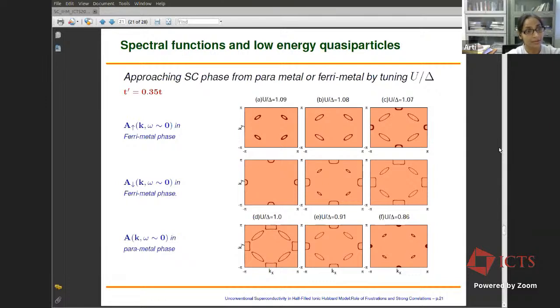And as you decrease the electron-electron interaction, the electron pockets start becoming bigger, and at the point where the system transits into a superconducting phase, we see almost connected Fermi pockets. And similarly, you can see that if you start with the paramagnetic metal phase on the left side of the superconductor and increase the strength of the electron-electron interaction, which is shown in the bottommost panel of this figure, for the small electron-electron interaction we have very tiny Fermi pockets. The system doesn't have enough number of quasi-particles in it. And as you increase the strength of the electron-electron interaction, the Fermi pockets become bigger in size, and eventually they almost start touching, and that's the point where the superconductivity sets in.